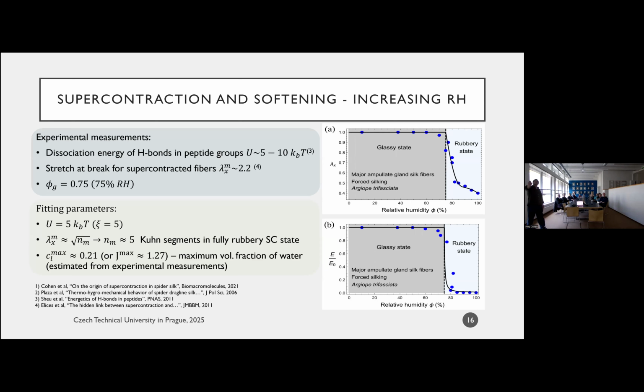So what you see here, this is the supercontraction stretch. This is the stiffness as a function of relative humidity. The dots are the experimental results. The curves are the model. And you can see that the model does a pretty good job at fitting this. Now, I should also point out, in the model itself, all of the parameters are physically motivated, right? So we don't have the classical fitting parameters. We don't have numbers that we could just throw in there to make it fit. But all of the model parameters are grounded in some physical quantity.